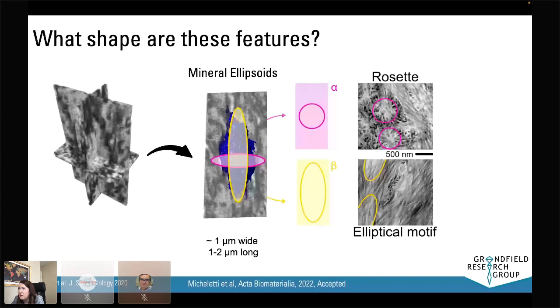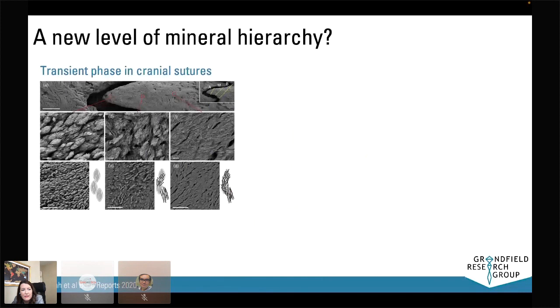So we're wondering if this is a new level of mineral hierarchy. Around the same time as we published our work, our colleagues in Sweden did some scanning electron microscopy where they removed the collagen from their bone tissue, and they saw similar ellipsoidal structures. They called these marquees, and they actually saw the evolution of these structures across cranial sutures. Their hypothesis is that these are maybe a transient phase of mineral, and that the ellipsoidal structure changes with time. We were looking at a mature sample, and we saw these ellipsoids through the entire bone structure.